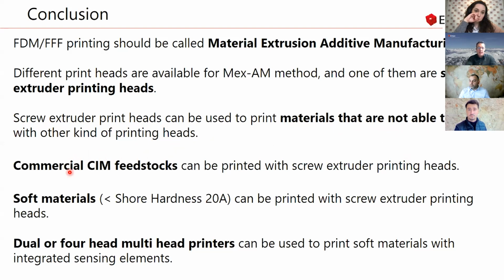And one example I tried to explain you is the commercial ceramic injection molding feedstocks, which you can nicely print with this kind of screw extruders. However, take into account you cannot use all kind of ceramic injection molding feedstocks or metal injection molding feedstocks. So you have to look a little bit what is their composition, because fusing you need anyhow during the printing process. Yeah, and therefore waxes might be a little bit a problem as far as we see at the moment.